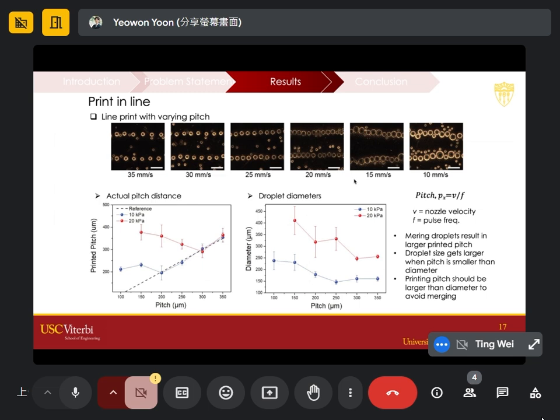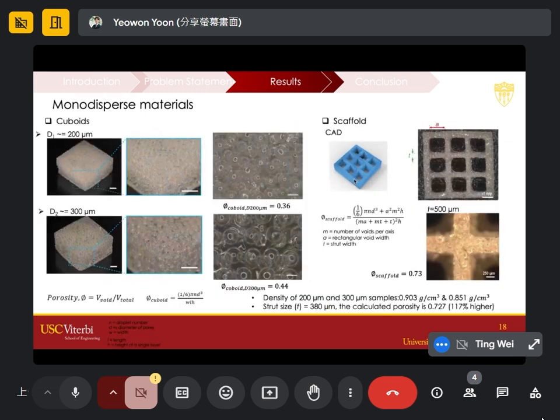Once we figured all that out, next we printed a few samples with 3D structure. This is the cuboid pattern printed at millimeter scale. The only difference between the top and the bottom is that the pore size inside is different. The top one has about 200 micron droplets inside. The bottom one is a little bit bigger, 300 micron, where the top one has about 36% porosity and the bottom one has about 44% porosity. Using a bulk material, we can only achieve about 50% porosity. So in that case, we want to push it further.